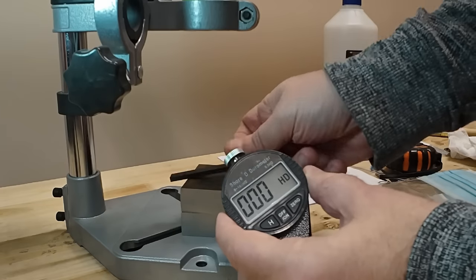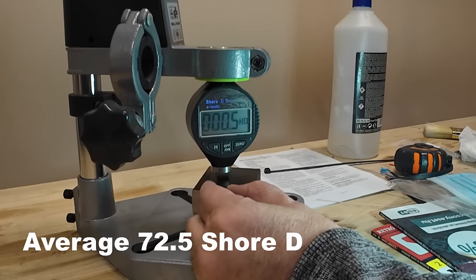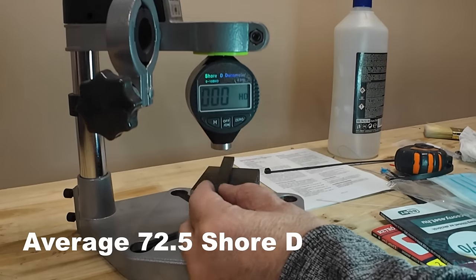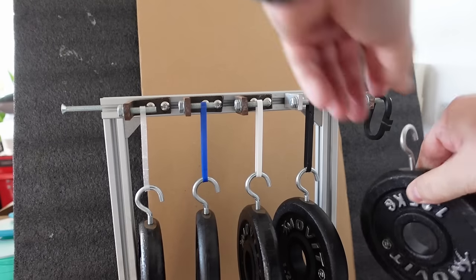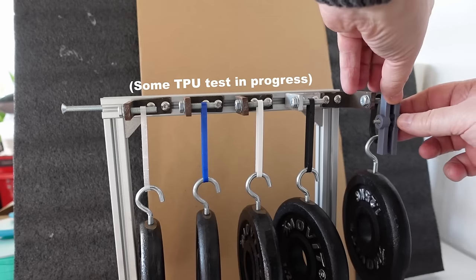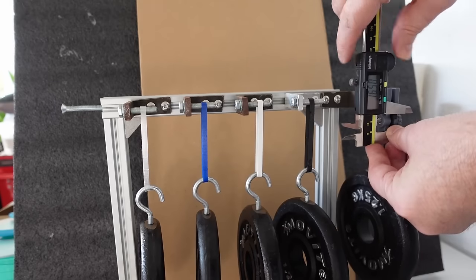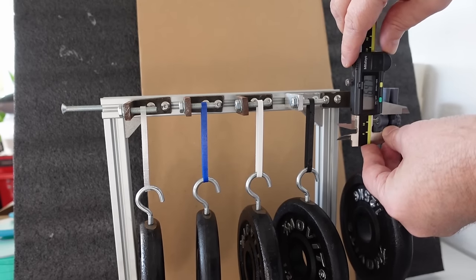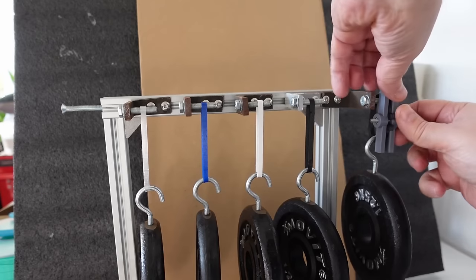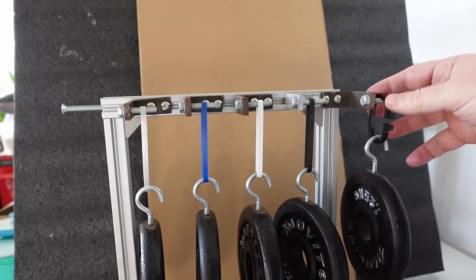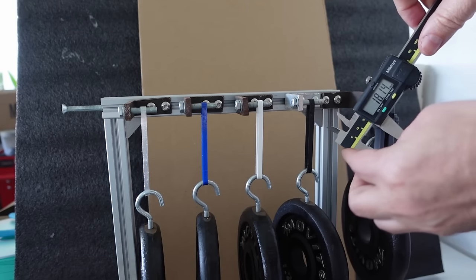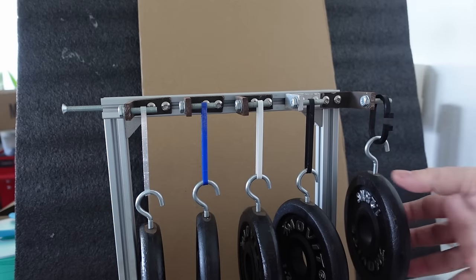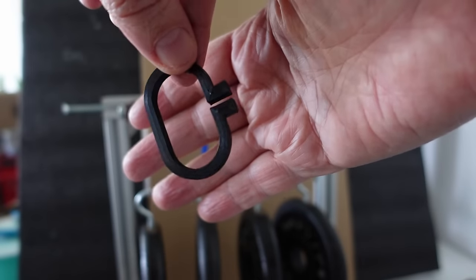And also I measured the hardness. I'm not sure why, maybe it is related to wear resistance and the average hardness was 72.5 which is quite hard material. And now a regular creep test. The load is 1.25 kg and I'm locking the position for more accurate measuring where I will measure the distance between two reference surfaces. And this is the first day. And I'm repeating this every day. And this is the fifth day. And now I'm removing the load. And almost no deformation on it.